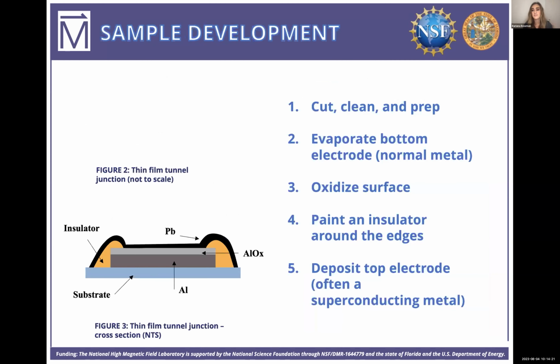So I spent the first half of my summer making samples and learning how to do all the steps. One of the first things I made was an aluminum lead tunnel junction, which is pretty well understood. So this was really a learning experience for me so that I knew I was making high quality junctions. The way that I did this was by first cutting, cleaning, and preparing a sapphire substrate. I would then evaporate a metal onto the surface. This is the bottom electrode and a normal metal. In this example, it's aluminum.